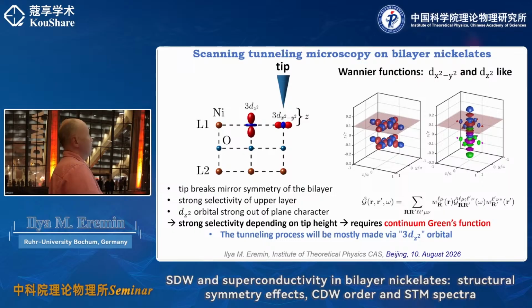But what is important for me now is that, suppose you come with a tip and the tip stops at a certain distance with respect to the surface. Then effectively, even if the STM tip itself is an s-wave function, the tunneling into the system will have a different orbital weight. The way to do it is not to take a lattice Green's function, but a continuum Green's function. So you take a lattice R-dependent Green's function which takes into account the matrix element, and this matrix element is your Wannier function. Whatever you calculate at the lattice level in your Green's function formalism will be dressed by the corresponding Wannier function when you perform the tunneling. So it's in principle a rather simple idea.